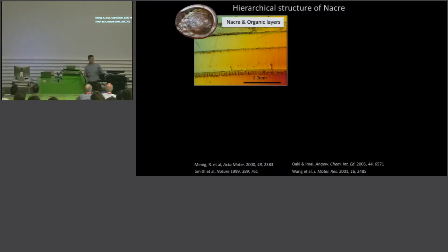So if you look more carefully at this seashell that is passing around, the first thing you will see at a macroscopic scale is that there are these larger layers in the hundreds of micrometers scale. So this layer here is the nacre layer that we will be talking about. And this is generated during summer. Then, during winter, the organism stops producing nacre and produces instead an organic layer, which is called the meso-organic layer.